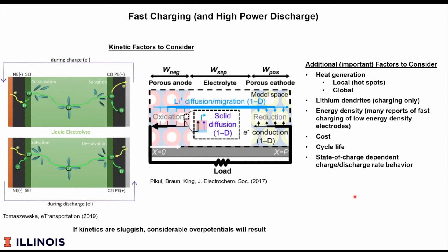And so I just have a few graphics here and references that you may be interested in referring to. If we think about lithium during charging, so we have lithium ion, it's in an electrolyte. This could be a liquid or a solid electrolyte, but in most cases today, it's in a liquid electrolyte. And so that lithium is highly solvated by the electrolyte. So as you charge the battery, electrons are going to come in and lithium ions are going to come in. So a number of steps might occur. That lithium must be desolvated, and so there is some energy to desolvate as well as the kinetics of that desolvation. Until that desolvation occurs, the lithium cannot go into the electrode.